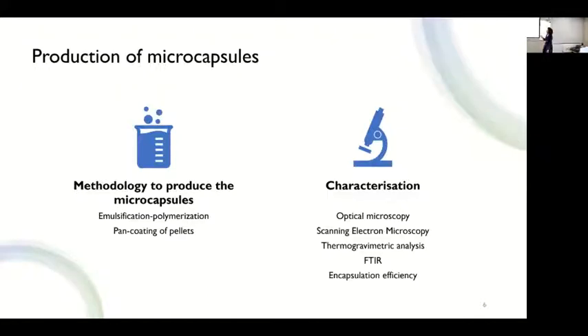And another thing that I think is very important to mention at this stage, and for you to bear in mind when you're reading papers that are using capsule-based self-healing, is that the characterization step is very important for these produced microcapsules. Because it's very easy when you hear Dave saying that you pour this phase in that other phase, and then you change the pH, and then the shell forms. Swelling is laughing. It sounds like making a cake, isn't it? You just pour in one thing and the other, and you change the pH, and then you form the shell. It's not that straightforward, and not necessarily because you mixed everything together, the capsule was formed.